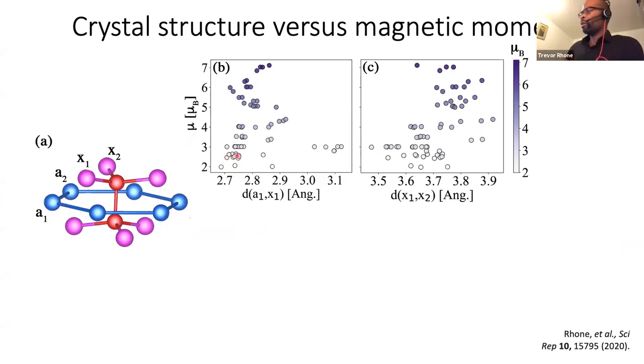And we see that there's some variation in the data, and at some value for this A1, X1 distance, mu tends to be large. Okay. We can also plot this distance between X1 and X2, this distance here. And the trend is, as you make X1, X2 larger in this data set, the mu tends to grow bigger. So there's some link between the structure and magnetic properties.